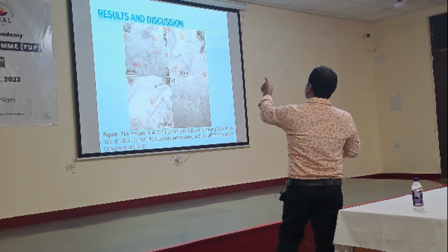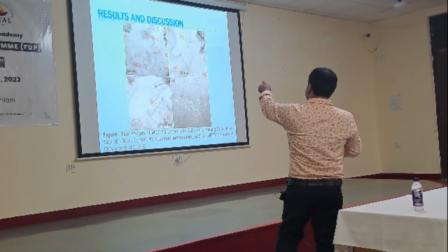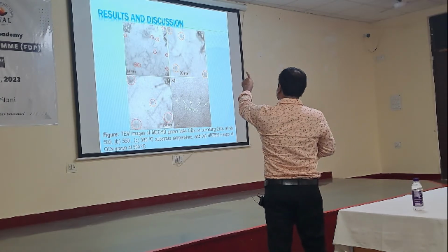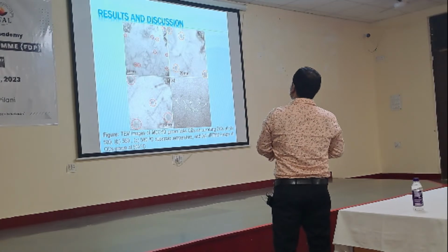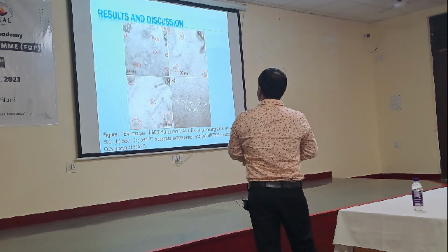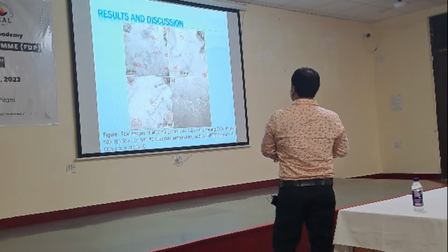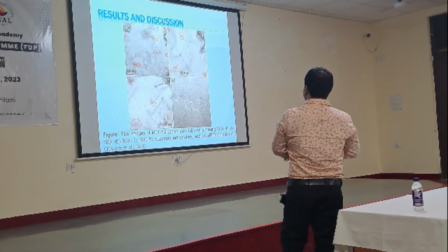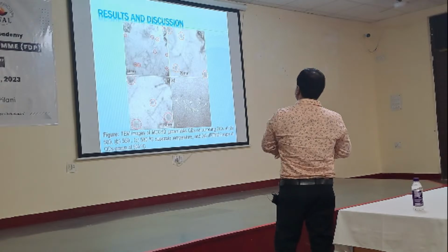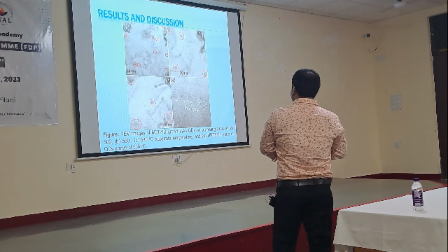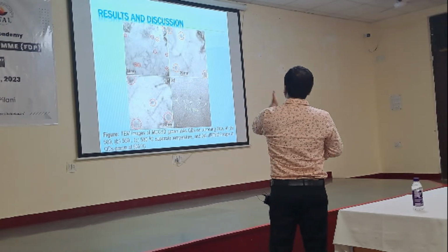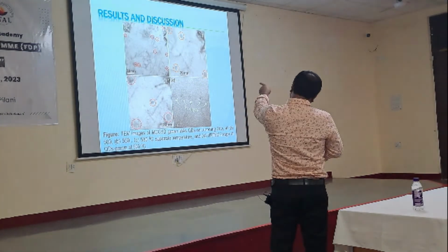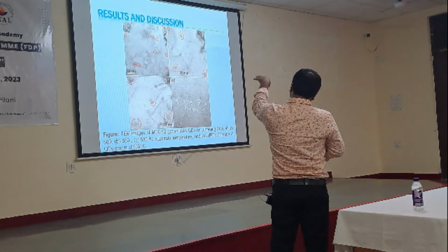You see your quantum dot is that black spot pattern, which confirms the formation of quantum dots in all the cases. First one is your 500 degree. To ensure the formation of quantum dots, I have experimented with both AFM and transmission electron microscopy. And the number D is your HRTEM image. You can see the crystal lattice also. You can see the lattice fringes there, parallel lines.